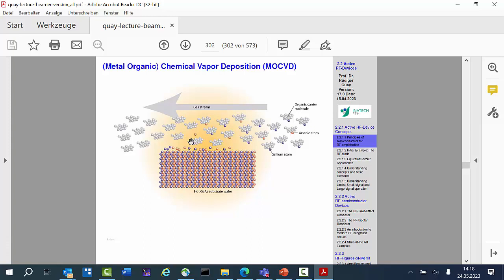Yeah, in combination with the temperature, and also the total pressure of the other gases in there. For example, hydrogen and nitrogen, which are also in there. You get a mixture, and the target is that these polymers, which are essentially decomposing, and the organic part goes off, and they drop the metals, and there's also the arsenic in this case, or some other group 5 material, and there could be nitrides, and then one-to-one you get a composition of this material. So for example, this is now given for gallium arsenide, or could also be gallium nitride.